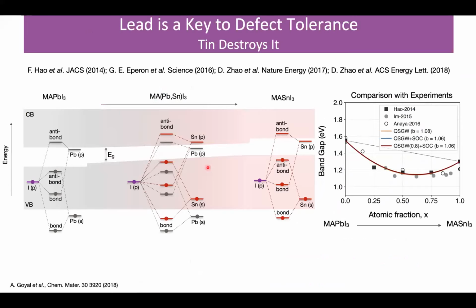Now, we have the defect tolerance, but we can mess it up, right? Most notably, if we move away from lead and go to things like tin, in this case we're using that destruction of the defect tolerance as a functional tuning knob to change the electronic gap. But we're also creating a lot of other defects that have low formation energies that are readily accessible. Particularly in the case of tin, it will want to create a vacancy and will want to p-dope the layer.